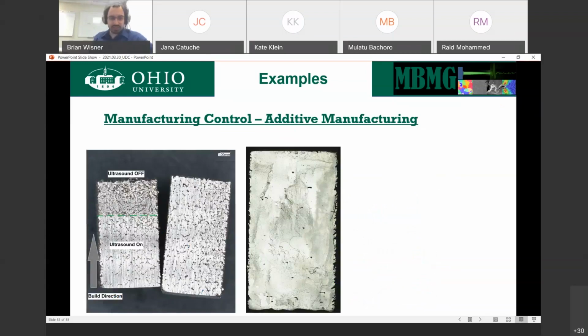In this particular case, what we're trying to achieve is to use ultrasound to change the grain structure of the material during a 3D print. And ideally, we will be monitoring this to see if we're being successful live. Just by looking at this, we have two samples, one with ultrasound on and off. Both of these were built the same way. In the lower part, the ultrasound was on. In the upper part, it was off.